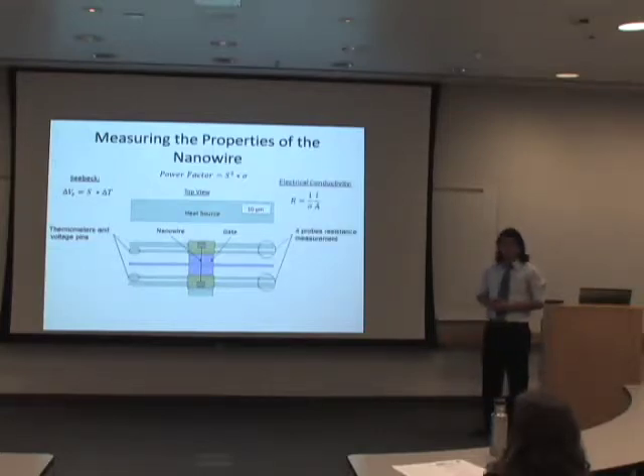For electroconductivity, we can measure the resistance of the nanowire across the length of it, and by knowing the length and the cross-sectional area of the nanowire, we can calculate the electroconductivity. This is just a four-probe resistance measurement, which basically means we run current through the outside electrodes and we measure the voltage drop in the inner electrodes.